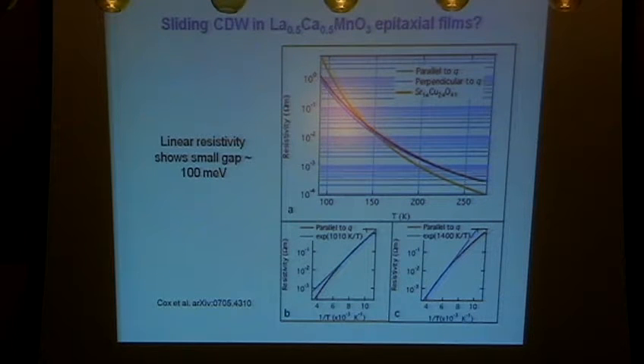It may even be, actually, that this particular material, you can move the whole stuff with an electric field. This is just linear resistivity. This is just to point out that this is actually a small gap semiconductor. The gap here is about 1,000 Kelvin, about a tenth of an eV.